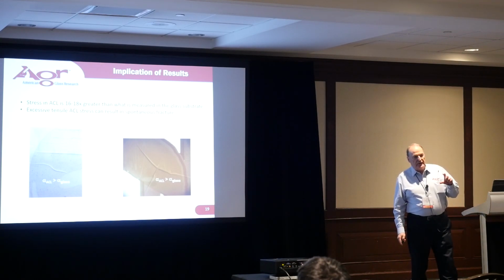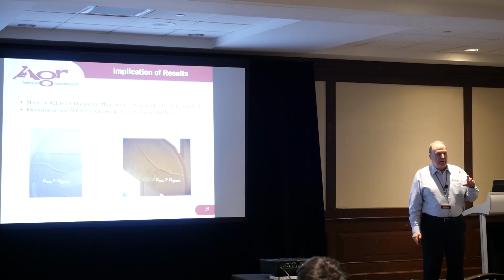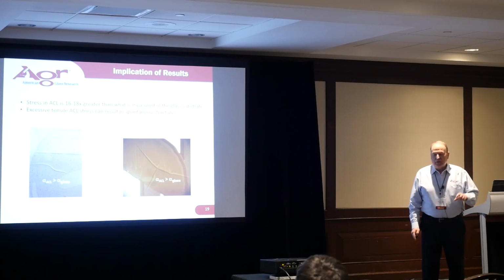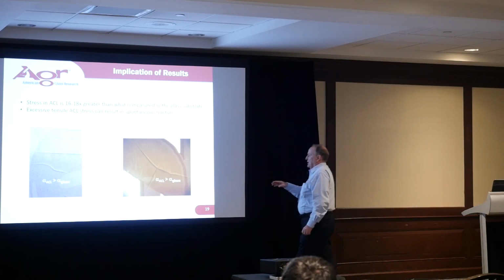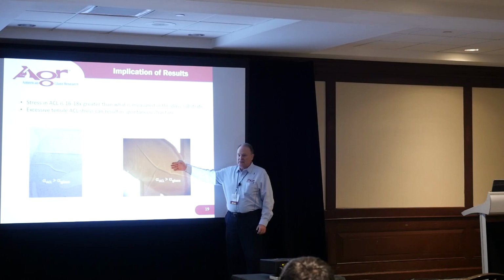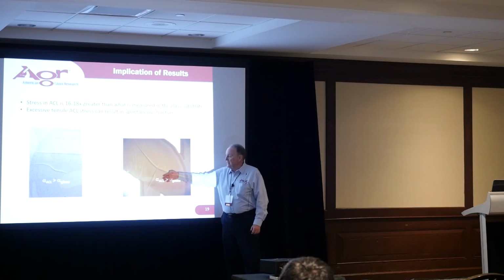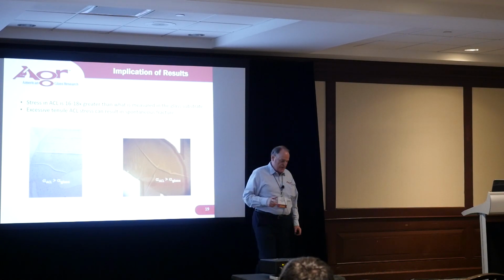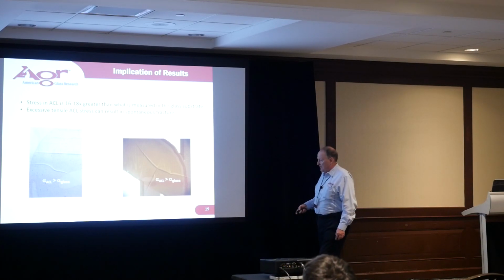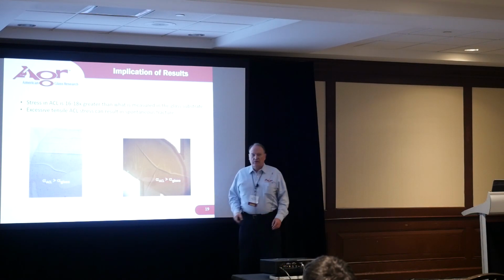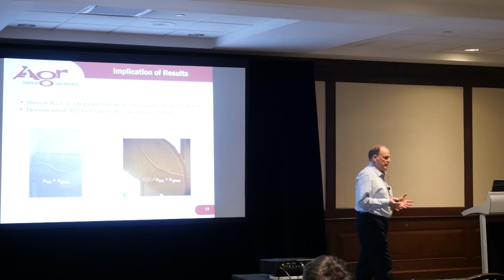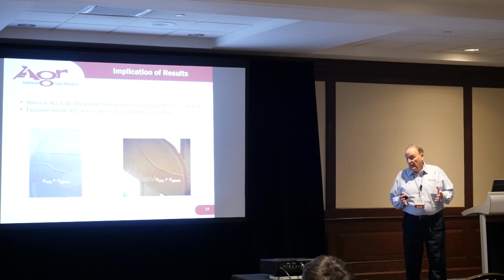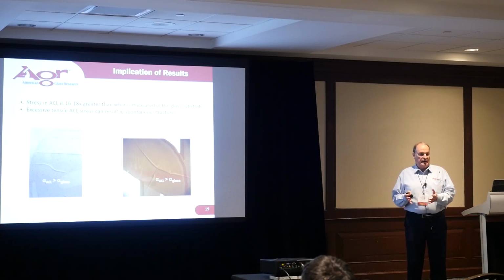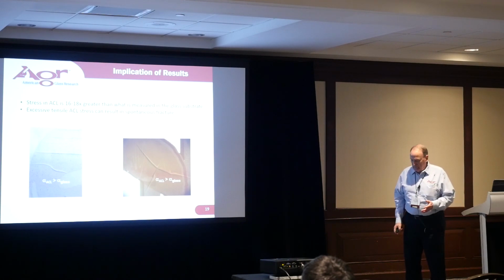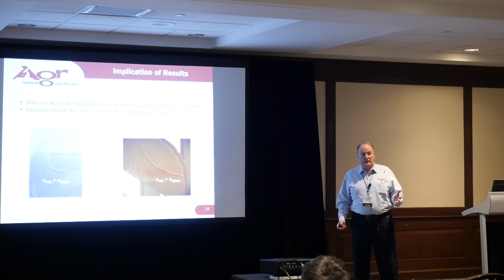These were segments of the sidewall of a refillable bottle. We cut the bottle apart so that we could look at the interface between the glass and the ACL. We're looking through the inside surface of the bottle so that we can see that interface. And in many instances, when the coefficient of expansion of the ACL is larger than the glass, you can see micro cracks being generated in the ACL. And sometimes those micro cracks penetrate through into the underlying glass surface. And where we first encountered this was in fracture diagnosis of broken decorated bottles.